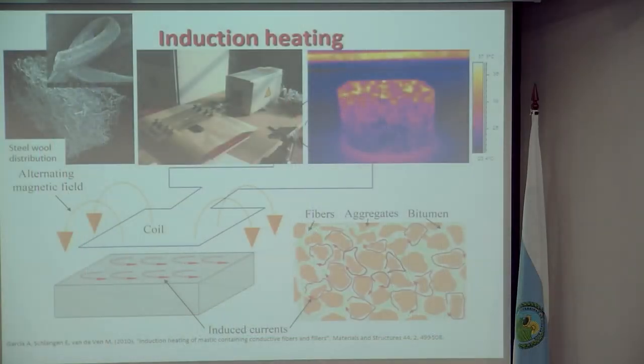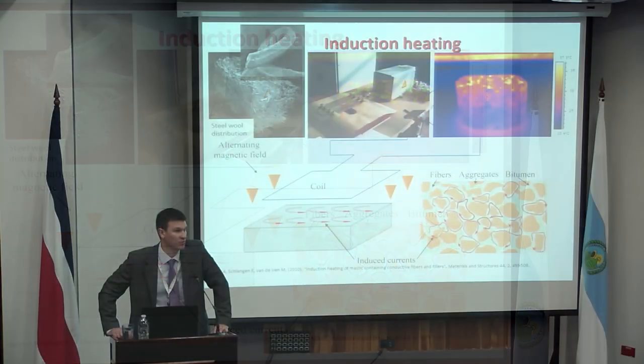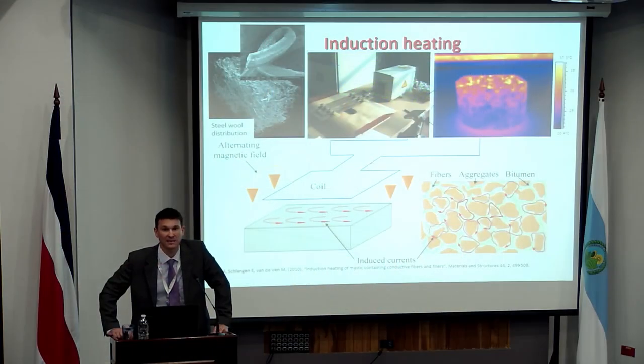We've got a little localized induction heating coil, and there's a bit of science in terms of defining the actual parameters of that coil. But once those have been defined, it's a fairly easy technique to produce specimens and then subject them to some form of induction heating, induction healing using the coil. It's localized heating, so you're not effectively heating up your whole specimen, which is what you would have if you had some kind of infrared heating approach. With the induction heating, you're only heating up the metallic sections, which are usually associated with the bitumen.